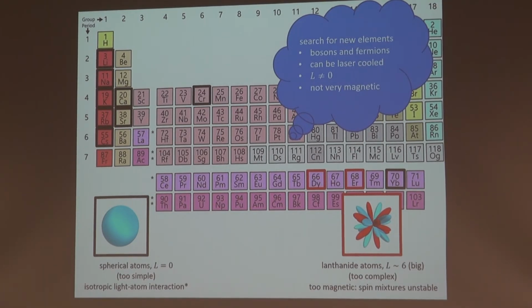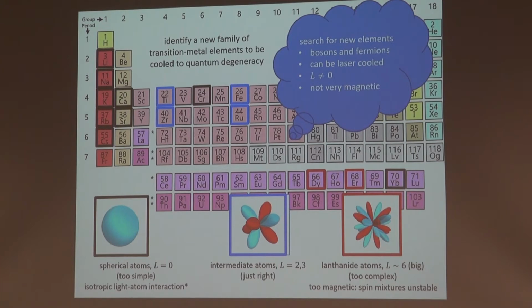So we looked around the periodic table through the NIST spectral databases, and we looked for elements which had a variety of isotopes, where the laser cooling is not ridiculous, where there's non-zero angular momentum in the ground state, but not so much that the atom is also very strongly magnetic. And we came up with the following, that we believe that the atoms in the titanium group and the iron group actually are quite amenable to laser cooling. And we've started an experiment to laser cool titanium atoms in particular. I'll tell you a little bit about that.